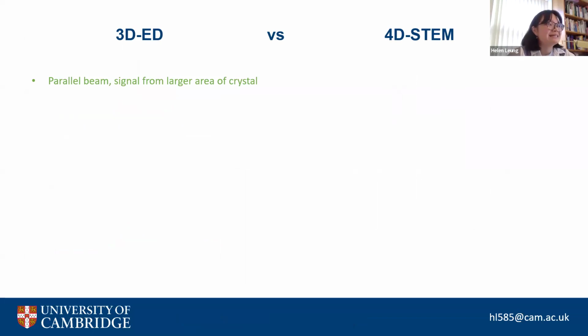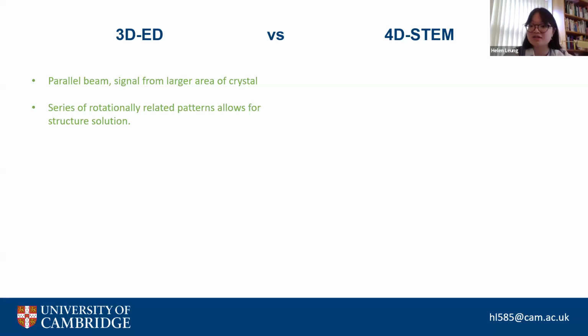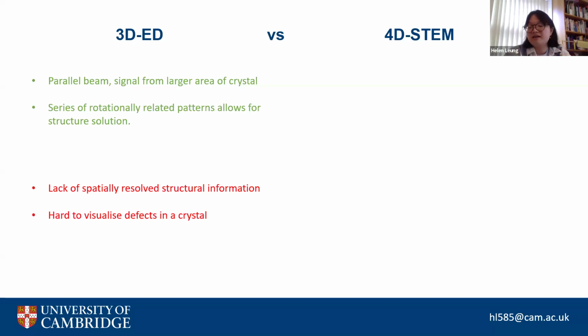3D versus 4D STEM. So with 3D I've shown you what you can do. You have a parallel beam, you get a signal from a larger area of the crystal, you get a series of rotationally related patterns, and that allows for structure solution. So that's very important, especially if you have a completely unknown phase or structure. But what it doesn't allow you to do so well is to really see what the distribution of crystallinity within the particle that you looked at looks like. And for example, it's very hard to visualize defects. So we don't know what the twins or the stacking faults or domains might look like and how they're distributed. Whereas with 4D STEM, you have very low signal per diffraction pattern, and you don't get any 3D information.